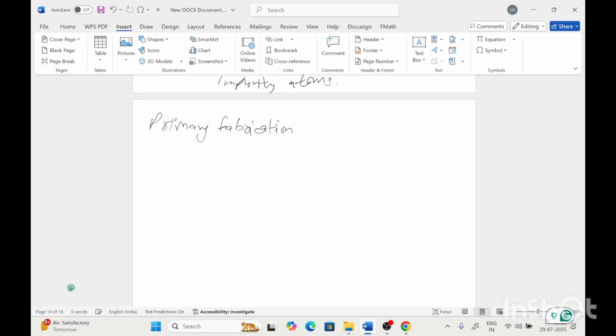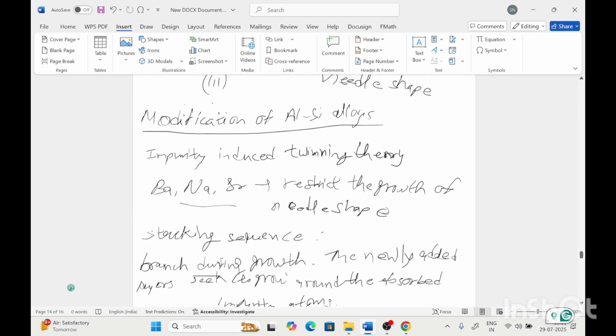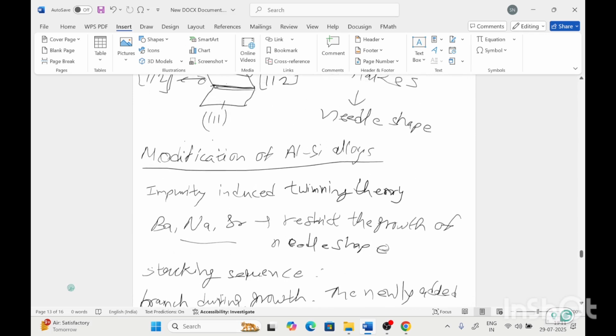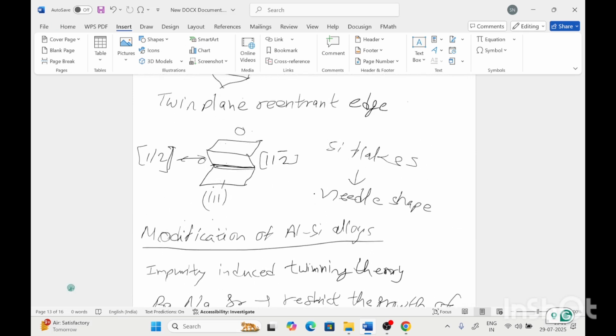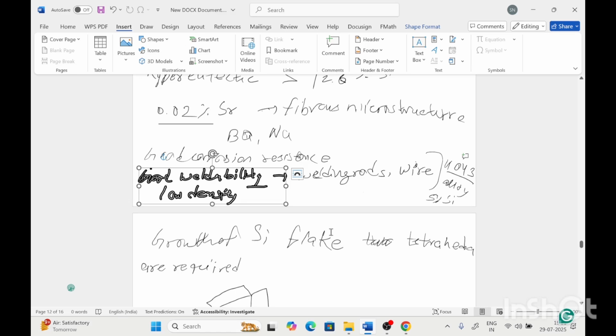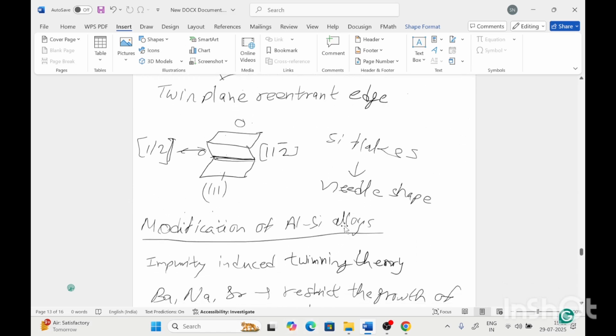Okay, maybe one question, ma'am. What is actually the twinning theory? Like impurity induced twinning theory. Yes, means in impurity induced twinning theory, the growth is around this twinning plane. So twinning plane is 111 and direction is 112 bar. So the modifier atoms will attach here or in this direction, and as the silicon atoms come, they will have to adsorb on these modifier atoms, so the flake formation will break, means the sequence will break, and that's why the needle shape will not form. Okay, okay, ma'am.